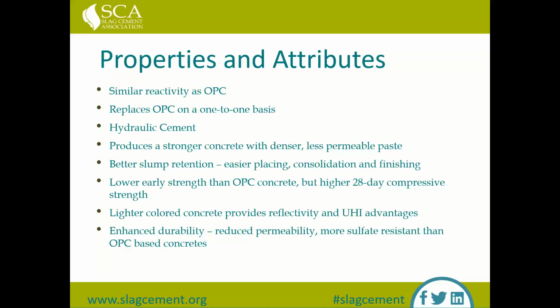So just a summary of slag and the properties and attributes. You're getting similar reactivity to ordinary Portland cement. There are differences in phases and mineralogy, but the reaction itself is similar. Typically, the replacement level of slag cement to Portland cement is 1-to-1. So if you hear us talk about a 50% slag mix, it's literally 50% of the Portland cement pulled out, replaced by 50% slag cement.